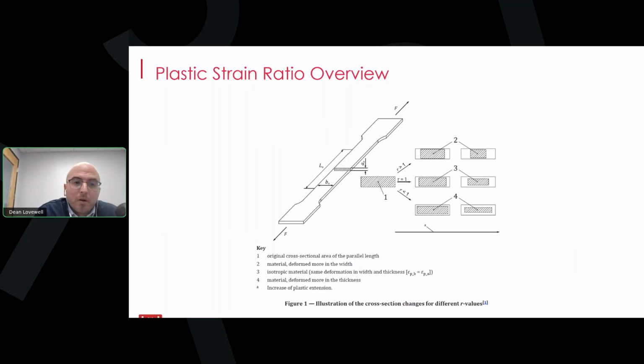In the middle, where R equals 1, the width strain and thickness strain are about the same. Here, the specimen deforms uniformly, both in its width as well as in its thickness. And then down at the bottom, where R is less than 1, this material would spread much less, as it deforms preferentially in its thickness.